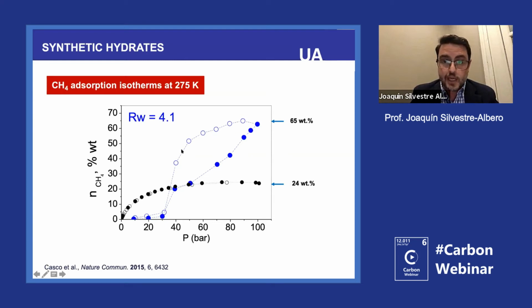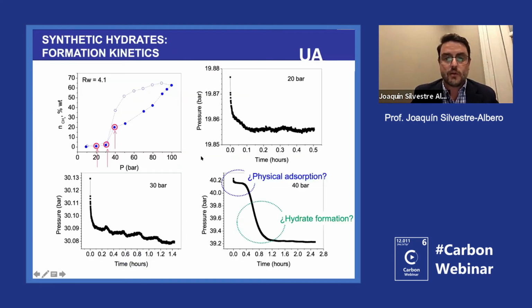And again, we have this hysteresis that is reflecting that something is happening in the cavities of the carbon. Before I told you that in the natural environment, the growth of these gas hydrates takes sometimes even weeks, because once you make the first film or the first layer, everything is very slow. And something nice about the carbons is that if we pay attention to the point of 40 bars, the first that we have the jump, and we go here to the bottom where we have the variation of the pressure in the manifold as a function of time.